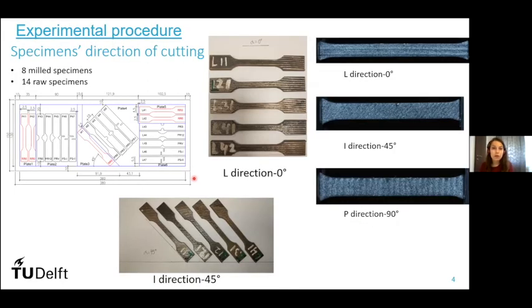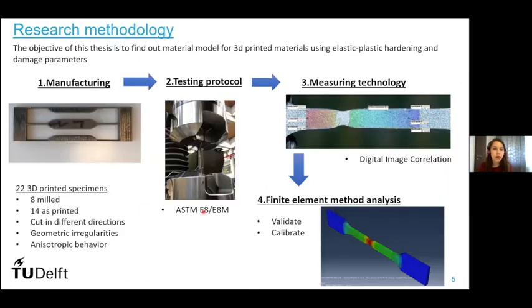We used the smallest type of specimen, in order to cut from the plate as many specimens as we could. And also the specimens were cut from the plate in a longitudinal, inclined and perpendicular direction from the printing direction. Also in the pictures you can see the roughness that is alongside or inclined or perpendicular to the cutting direction. I analyzed 8 milled specimens and 14 as printed specimens. The testing protocol was made in accordance to the American standard. The measuring technology was digital image correlation, and to validate and calibrate the results, I used finite element analysis with the objective of finding out a material model for 3D printed materials using elastic plastic hardening and damage parameters.